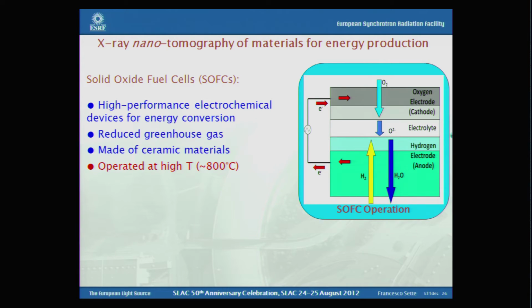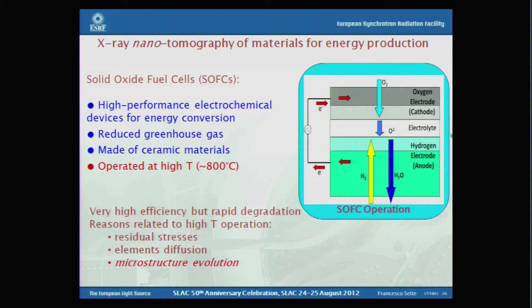These, as you know, are high-performance electrochemical devices. And today we are looking at them a lot for energy conversion. They have advantages like reduced greenhouse effect. They are made of ceramic materials, and as a consequence of that, they operate at very high temperature, typically about 800 C, and this is one of the main problems for their use. For that reason, they are very efficient, but they also go through rapid degradation, and the reason is this high temperature operation. So you have residual stress, elemental diffusion, the evolution of the microstructure, and so on.